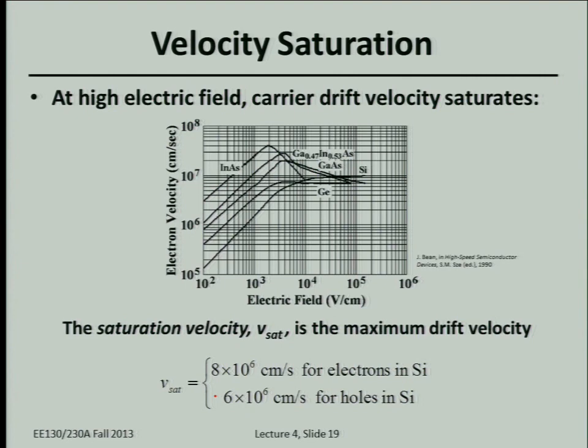Okay. So this is actually a measured mobility plot. I mean, so basically, how do we measure mobility? We plot the electron velocity or the hole velocity versus electric field. As I mentioned, in reality, we do see saturation around 10 to the 7 centimeters per second. Okay, so the mobility values are only valid at low electric fields. And as I mentioned, it's close to 10 to the 7 centimeters per second for electrons and holes in silicon. Okay?